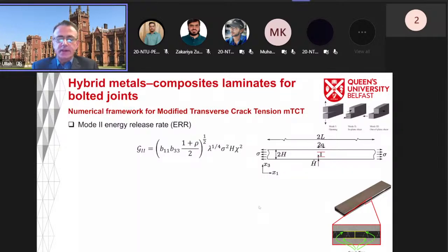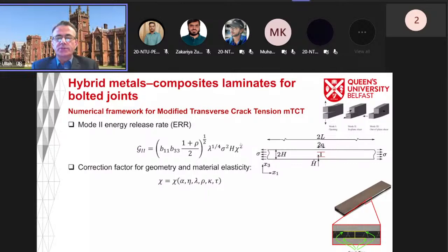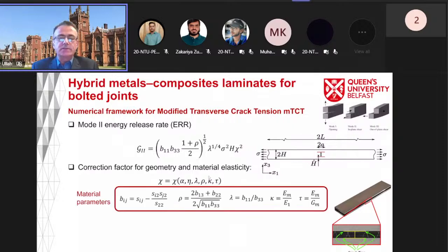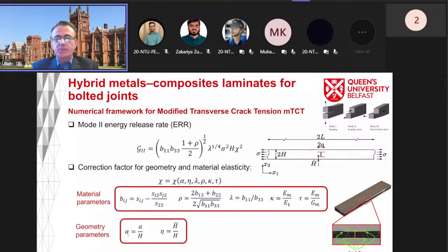In our case, this is the equation for the G2. In this equation, we have this X, which is what we call the correction factor for geometry and material elasticity. This X is a function of all these different parameters. In these 2 equations, we have some material parameters which depend on the elastic constants, and some geometry parameters of this specimen. For example, we have alpha, which is the ratio of the length of this crack divided by the thickness of the laminate. And then we have the ratio of H and h, where H is the total thickness and the small h is for the metal part.